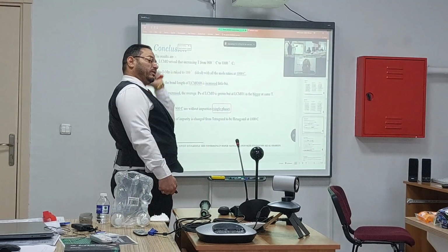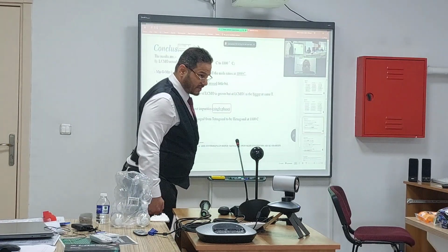As the temperature increased, the average particle size grew, like I illustrated in the previous plot. Lanthanum 5 and 10 molar ratio at 900 degrees was interesting because it was single phase without impurity, better than 1 molar ratio. The crystal system of the impurity changed from tetragonal to hexagonal at 1100 degrees.